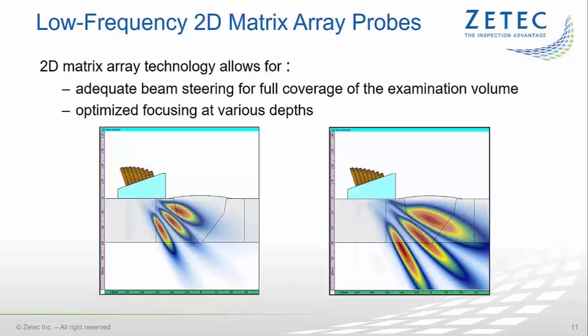All the benefits mentioned in my previous slide are also true for conventional transmit-receive probes, and this good practice has been known and applied by several probe manufacturers and NDE service companies as far back as 1980. But phased array UT, and more specifically 2D matrix array technology, enables a number of additional benefits. First of all, well-designed 2D matrix array probes allow for adequate beam steering to provide full coverage of the examination volume on the first half skip. Also, they can be controlled to focus at various depths and can therefore be used for a wider range of weld thicknesses.